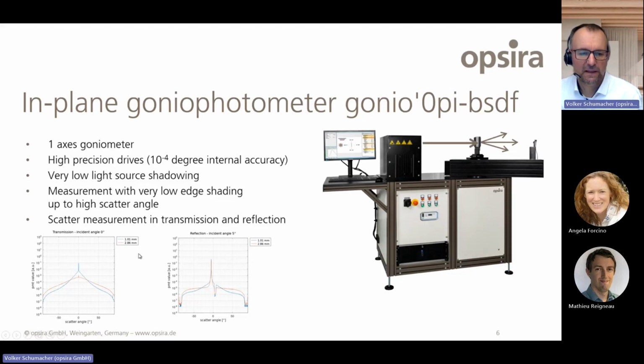On the side here below, we can see a transmission measurement. It's one type of material, but with 2 different thicknesses. The blue curve is 1 millimeter thickness, and the reddish curve is 2.8 millimeter thickness. For the 1 millimeter thickness in transmission, we still see some non-scattered light, and here we see the remaining part of the scattered light. For the 2.8 millimeter thickness, we only see a very low amount of non-scattered light, this one here, and this is all scattered.